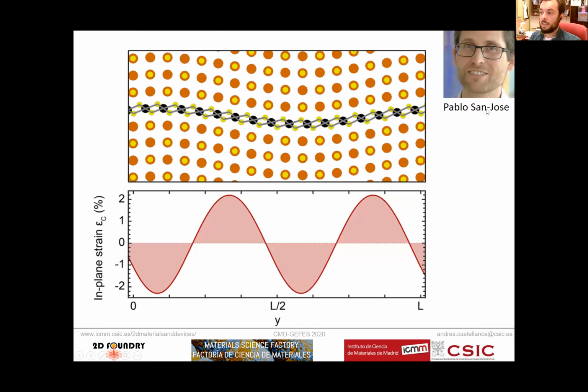Our colleague Pablo San Jose made a simple mechanical model, including the different terms, the interlayer interaction, the bending rigidity, the shear forces, etc., and found out that basically the interaction between the layers, the weak van der Waals forces, is strong enough to distort the lattice of the two layers in order to make these two lattices commensurate.